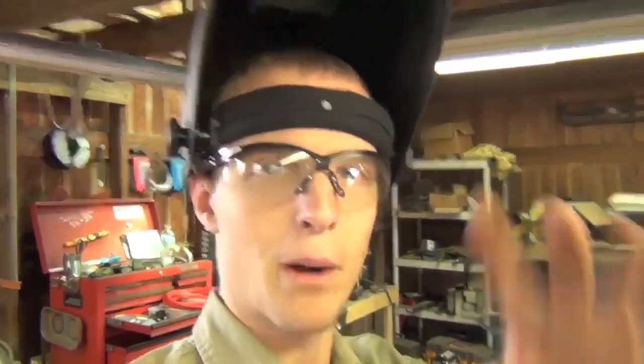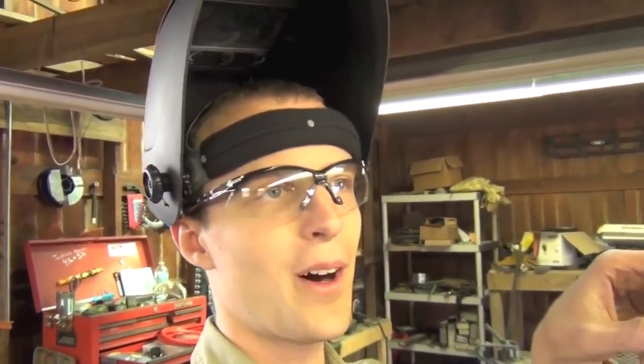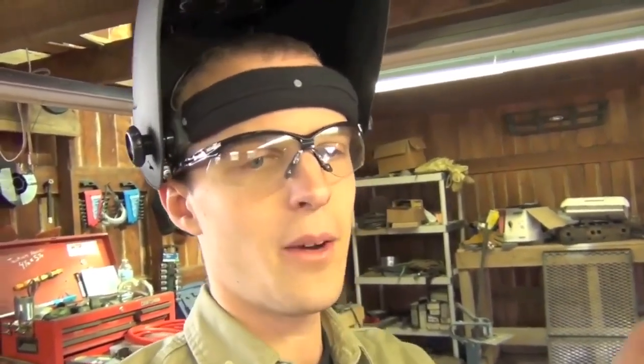But if you're going to MIG weld it, you're looking at 175, 200 plus, depending on the wire you're running and a few other variables. So unless you're running auto body sheet metal or really thin gauge material, you're probably not going to have issues with running too hot. And if you are, you're just going to burn through. If you're welding along and all of a sudden everything just falls out, you're running way too hot. That's how you know. Or you'll have undercut, which is when the weld sinks into the plate and there's an unfilled groove there, which is bad because A, it looks really bad, and B, that can cause a stress riser and cause your weld to fail.